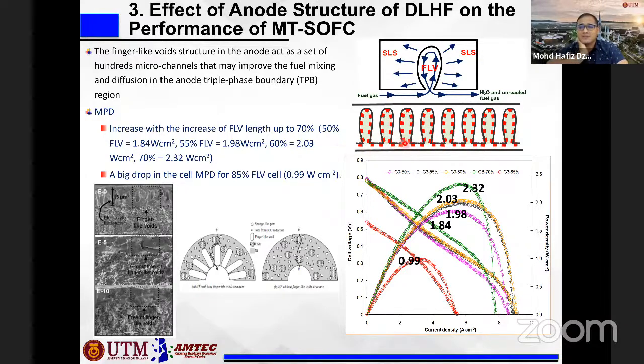So this asymmetric structure is good, but it has some limitation in terms of reduced mechanical strength. But I believe if you can change the finger-like structure into a better, bigger microvoid inside it, for example, if this pore can be made bigger, and there is a continuous pathway for the fuel to travel, in fact that is a much better structure.